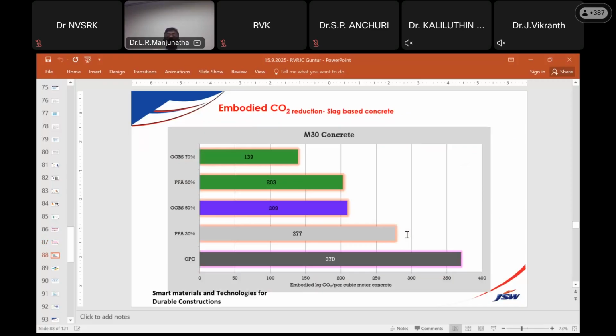This is an example of embodied CO2 reduction, slag-based concrete. A 70% GGBS mix is liberating only 139 kg CO2. Then fly ash, 50%, if I am using it, 203 kg. Compared to the OPC emissions of 370 kg for every cubic meter of M30 grade concrete. So you can clearly see how the emissions have been reduced.